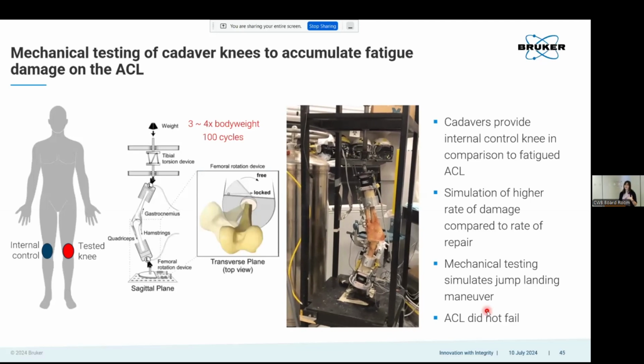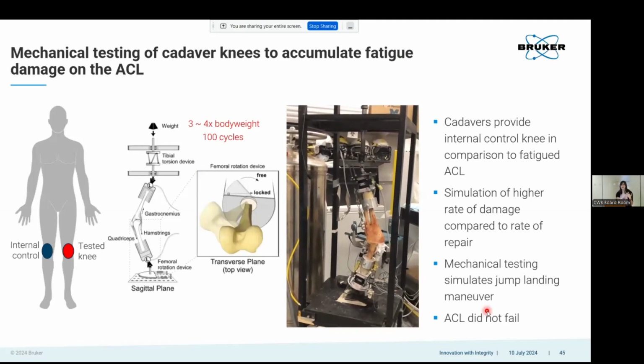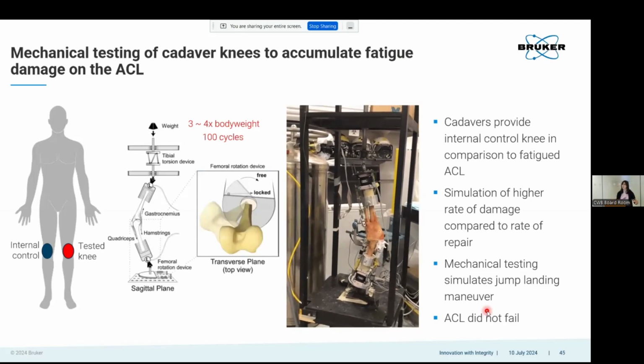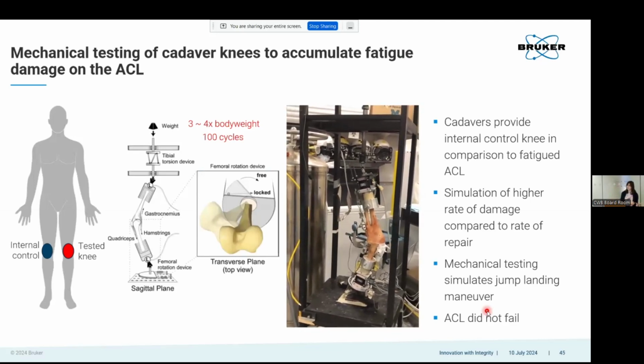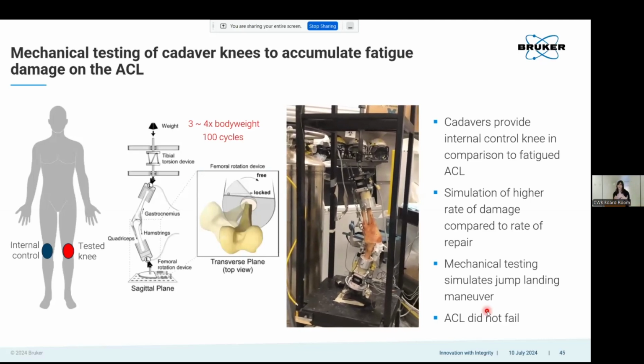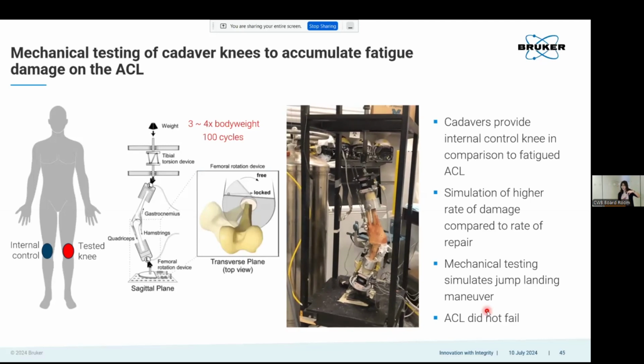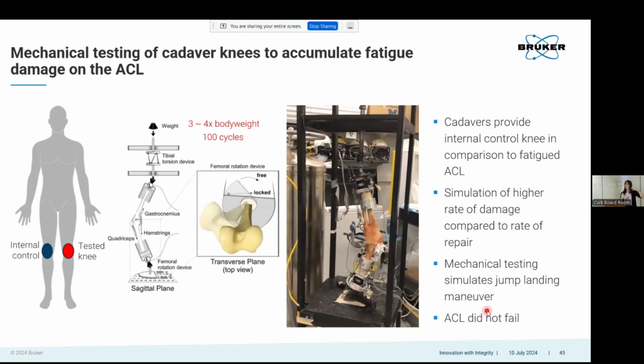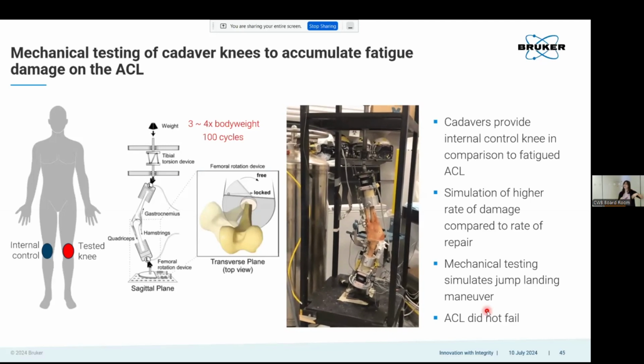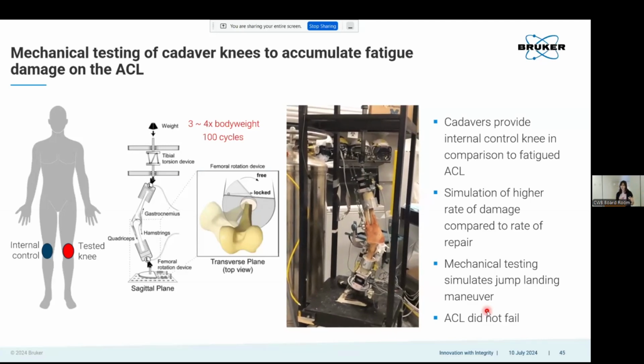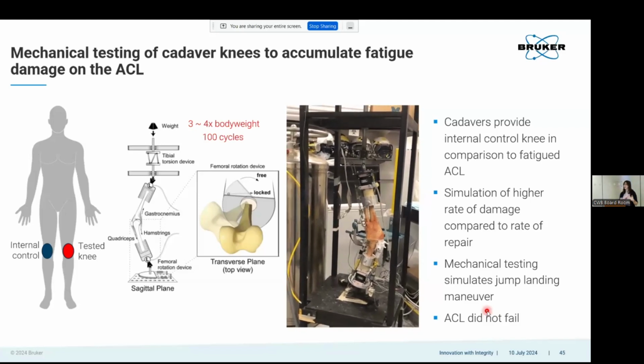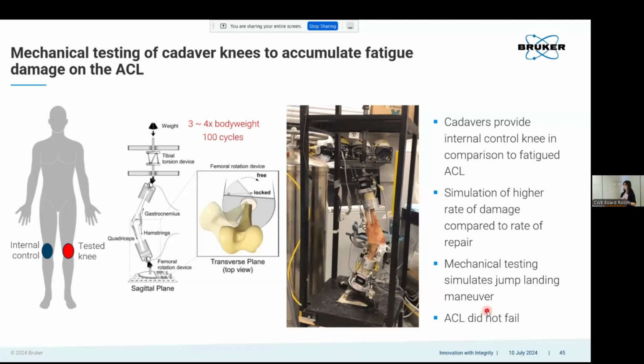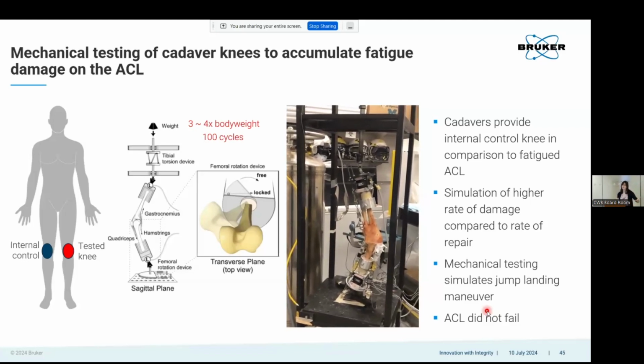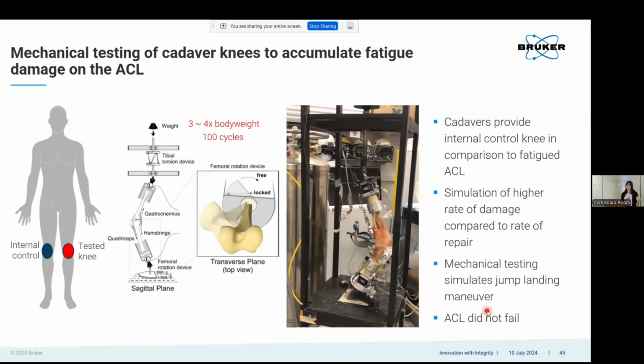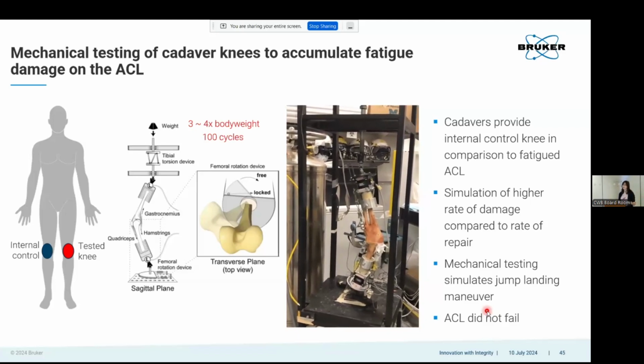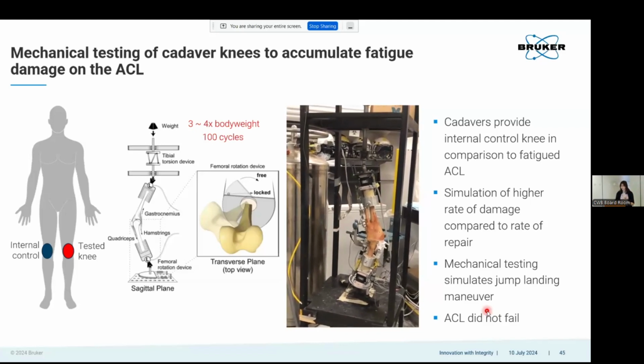But effectively what they did is they used cadaver tissue and they look at an internal control knee, right? A knee from the same cadaver, which should have had similar conditions, and then one which is going to be tested. They put it into this mechanical device and they simulate loaded jumps. So just somebody jumping over and over again with 3 to 4 times their body weight for 100 cycles. All things considered, this is not a critical injury, right? You can do this jump right now. Your ACL should not fail, and even over 100 repetitions, the ACLs in the study don't fail.